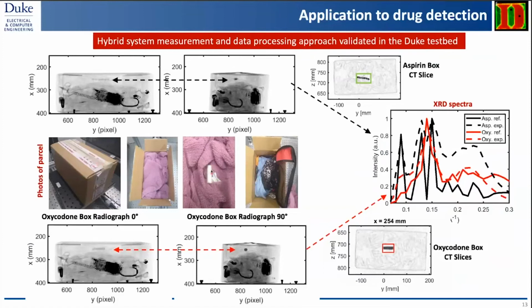So just an example of this, Josh had packed this box full of clothes and walkie-talkies and some pharmaceutical products, and made some very simple X-ray CT measurements and did just a very simple reconstruction. But you can see that the top box that had aspirin in it looks awful close to the bottom box that has oxycodone in it in the transmission measurements.